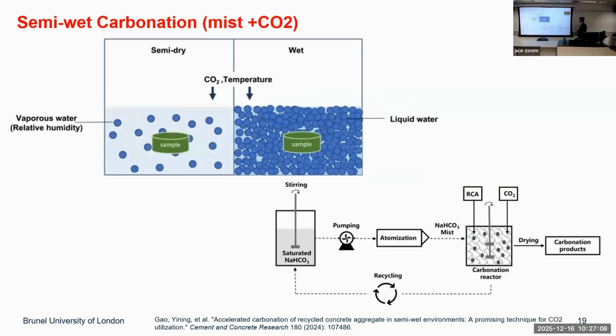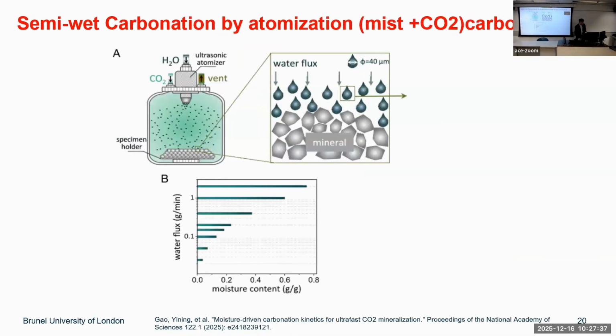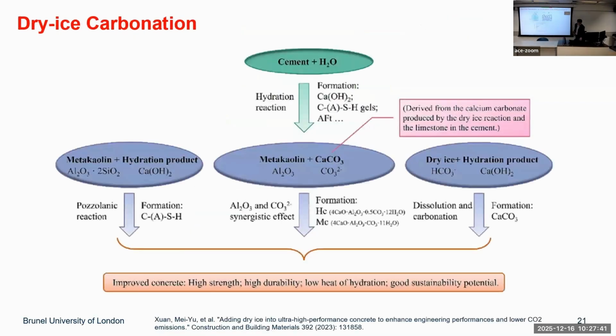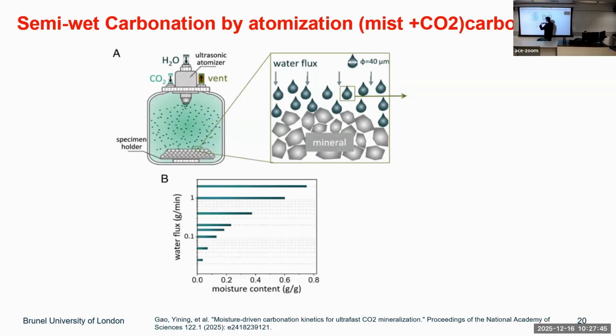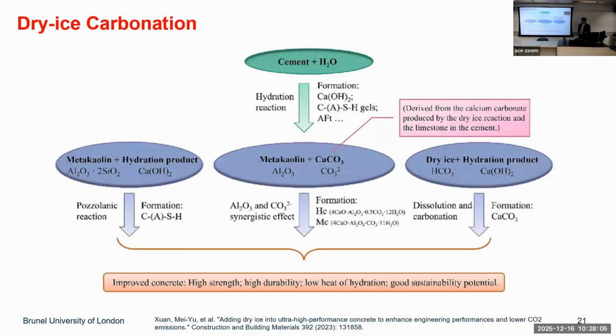Then they have semi-wet. The particles are regularly wetted with water in a humid environment. You can pump this saturated solution to accelerate the reaction between the particles and the solution. And this one uses an ultrasonic atomizer to keep a critical moisture level on the particles, and make sure they get maximum possible exposure to the moisture and carbon dioxide.